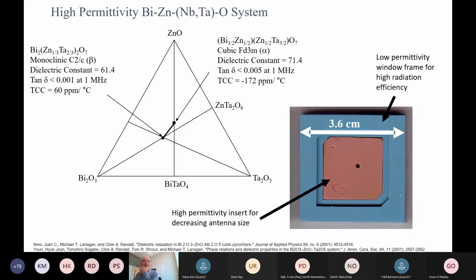Another concept we were playing with was an antenna idea where we had a high permittivity to miniaturize, but also then had some fringes of low permittivity to really help the efficiency of the antenna. And we worked really hard at the center material. In this case, it was a bismuth zinc tantalate or niobate. And as we started looking at these materials, we can actually tailor different phases. You can see here, this monoclinic phase had a 60 ppm per degree C, so positive, and this cubic form actually had a negative.